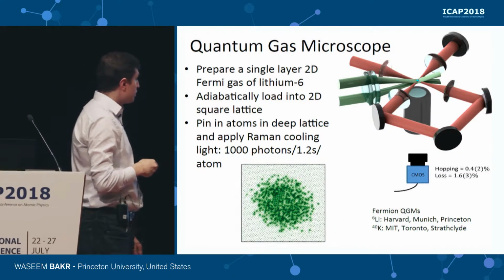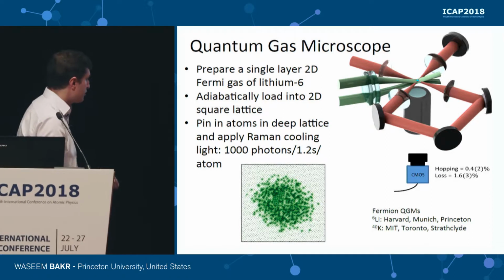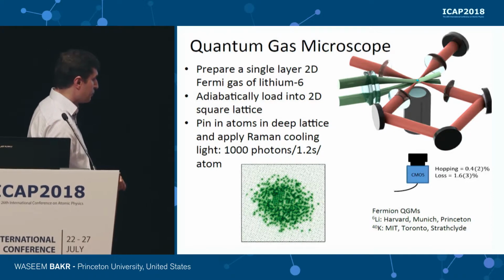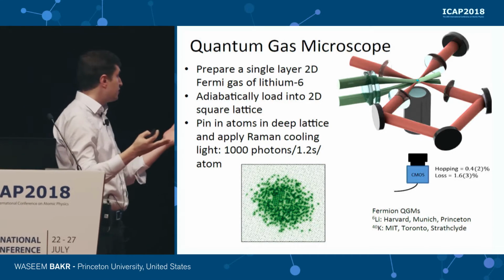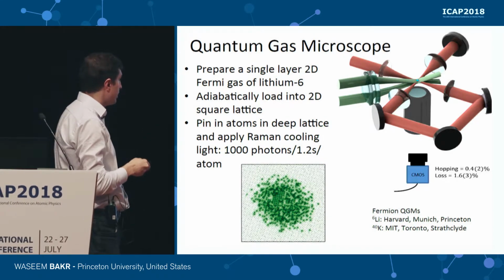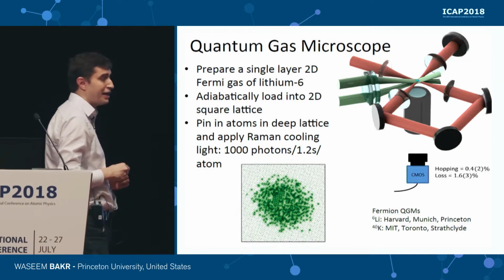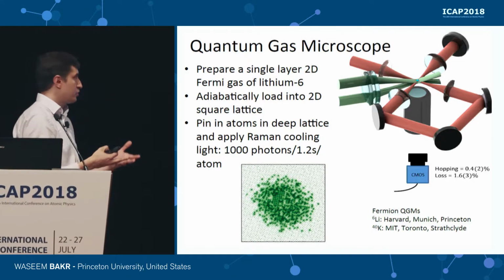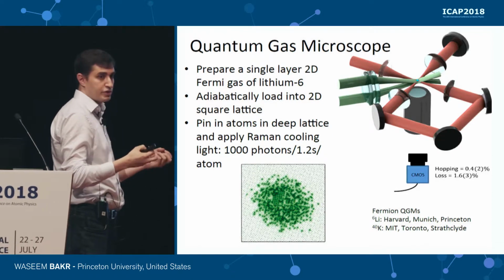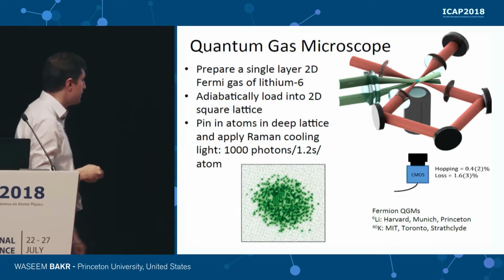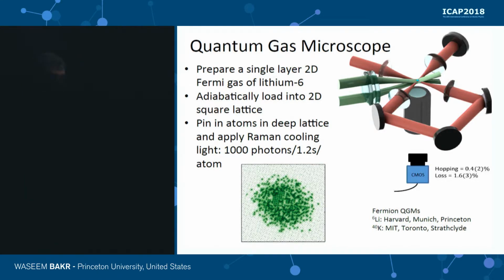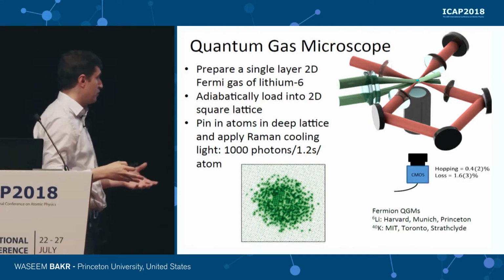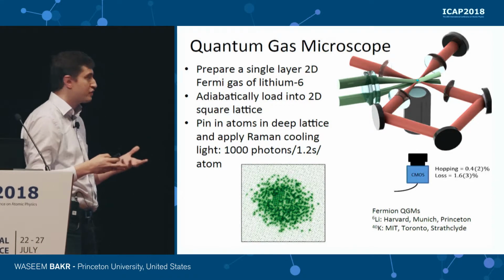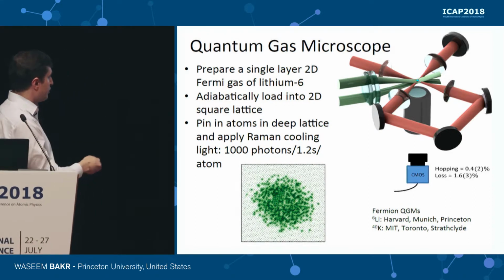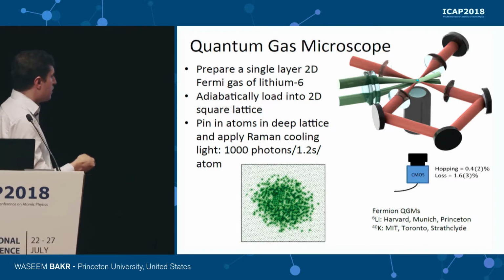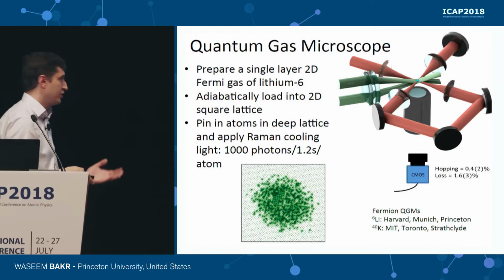So our setup is a quantum gas microscope, similar to the one that Christian talked about. It's also a lithium microscope. We have a 2D gas of fermions, which we load adiabatically into a square lattice. When we want to image the state of the system, we freeze the density distribution in a very deep lattice and scatter photons in a Raman cooling configuration. We can collect roughly 1,000 photons per second and get images like this, where during the exposure time, the hopping and loss rates are at the percent level.